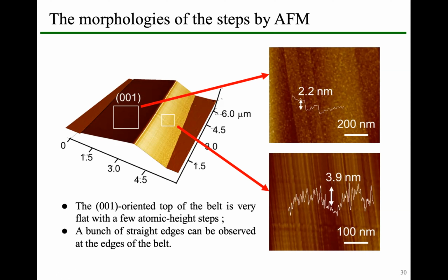I see, but what do you mean by the edge? That edge is kind of a collection of many multi-layer edges. Yes, exactly. Some of them are even layers, some of them are odd layers. Basically, if the layer is odd in thickness, then you have edge state. But if you have an even number, then you have hinge state, or this kind of slightly gapped edge state.